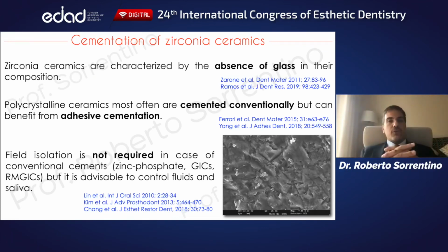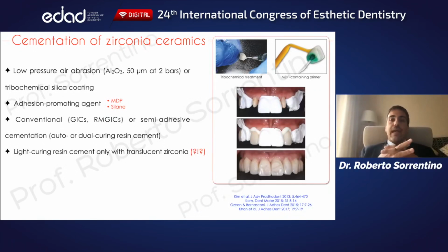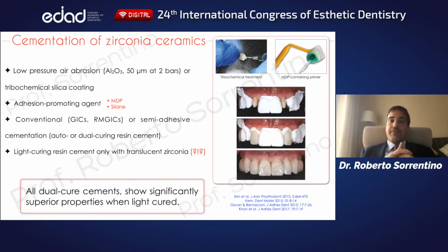Field isolation is not mandatory, but control of contaminants such as blood and saliva is always recommended. Zirconia has to be conditioned with both chemical and mechanical surface pretreatments, just like mild sandblasting and tribochemical silicoating. In case of simplified adhesive cementation, coupling agents such as MDP-containing primers and silane may finally improve bond strength. If you choose translucent cubic zirconia, you can go for light curing resin cements, but consider that it presents reduced translucency, and consequently it is always advisable to use light activated dual curing resin cements.